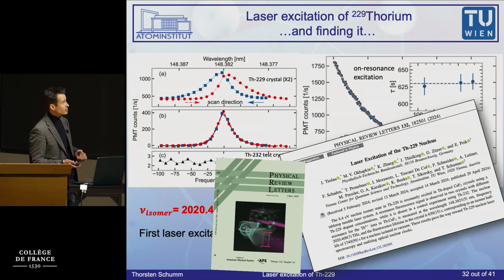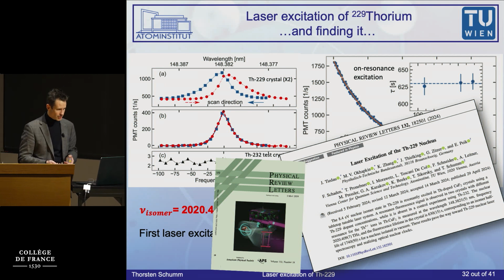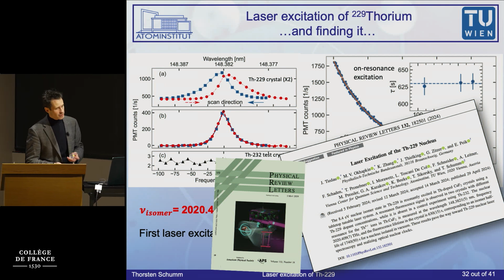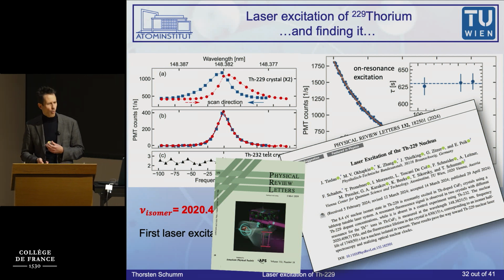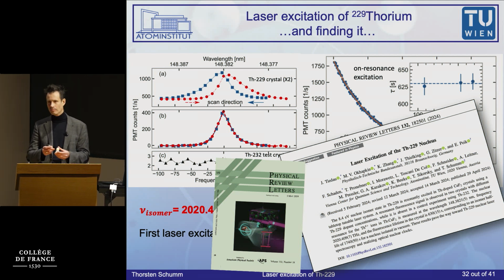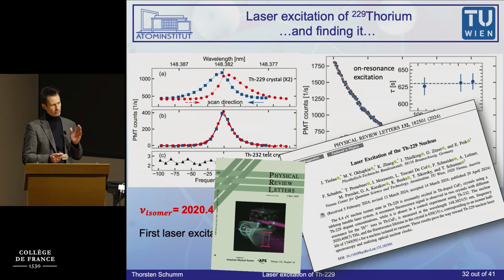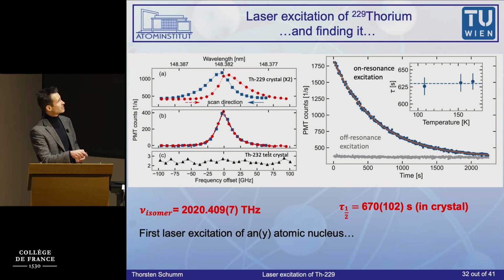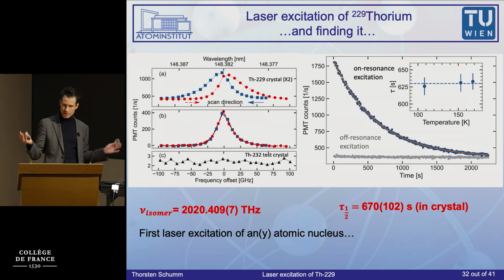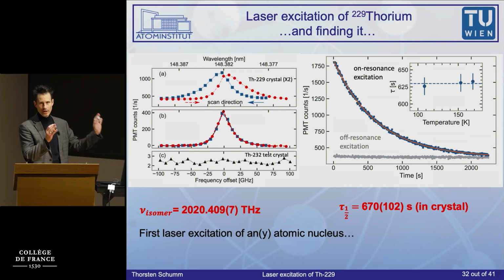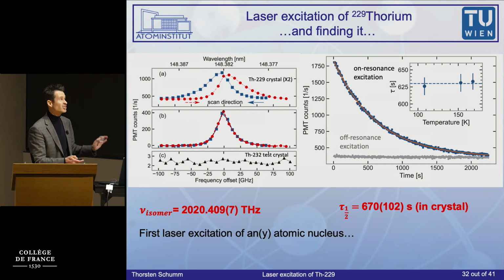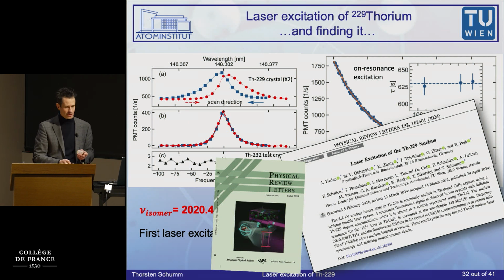And that, to our knowledge, is the first time that a nucleus was excited by laser. There was always this bad feeling nagging us: what if this is some defect, some color center in the material? It's unlikely because it has a narrow line width and a long lifetime. We did a test experiment where we did exactly the same but with the wrong thorium isotope. So we had a crystal that has thorium-232, which has a completely different nuclear structure and didn't respond, but still you don't really believe it.